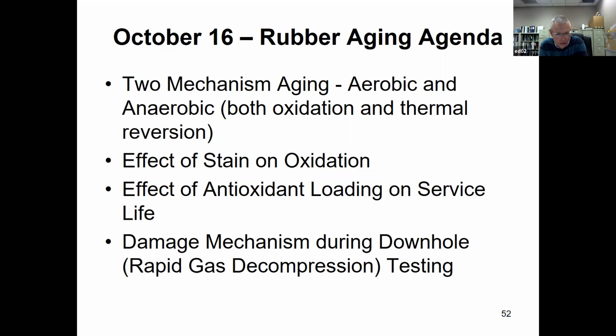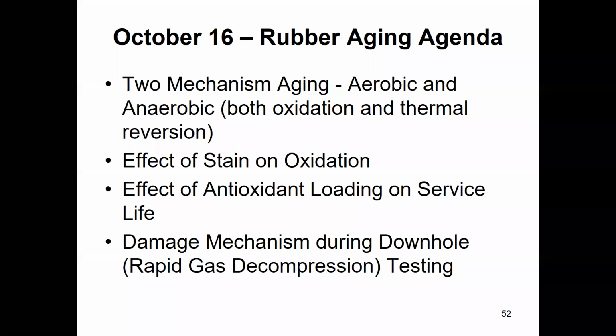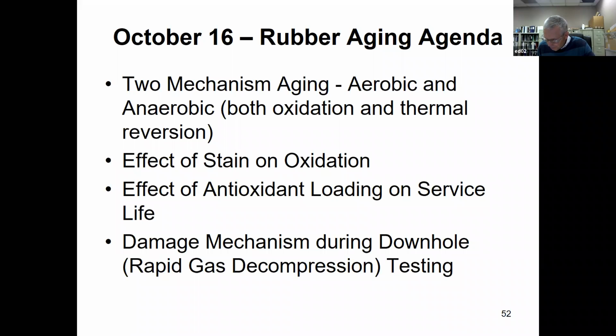So this is how I try to handle that. I don't have a lot of experience, but if you remember last week, we had that issue where the partial pressure was not atmospheric and there's a duty cycle, so we identified a shift factor in the oxygen consumption rate data to account for that. What I'm hoping to do in future studies is, we have clear glass oxygen consumption reactors, and put the reactor into the UV chamber, right? And so we can get the change in oxidation rate associated with the UV exposure versus the consumption rate without UV exposure and get a shift factor.